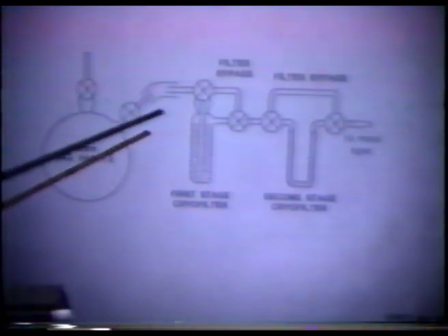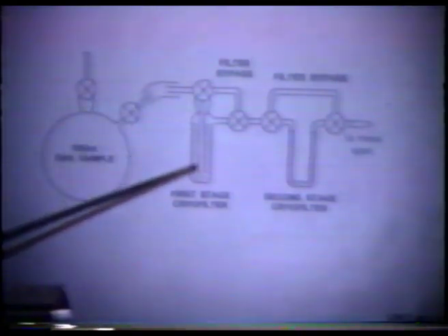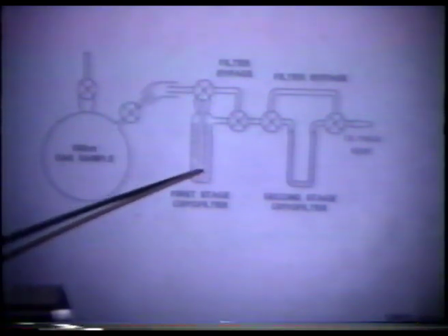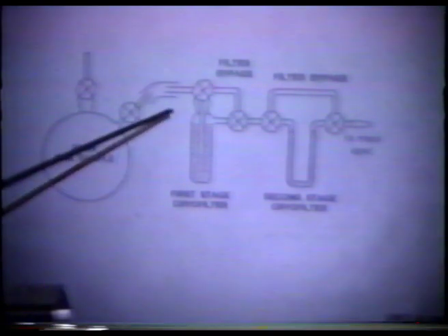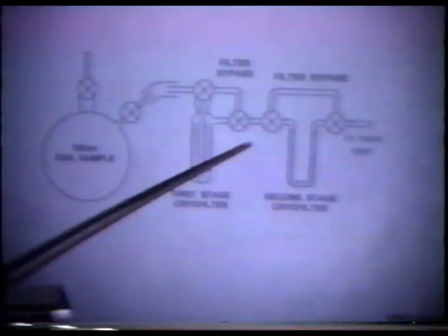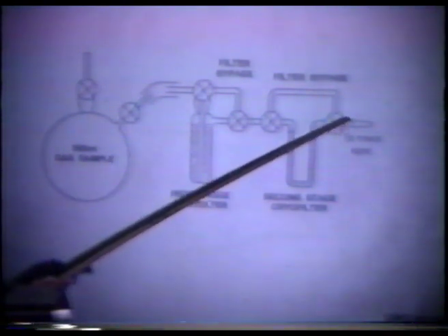In Texas, Ben Bush received these flasks, and to do the mass spec analysis, there's a lot of deuterium in here of mass 4. Now, deuterium of mass 4 is going to be a very big interference trying to measure helium. Therefore, we pass this through a cryo filter. This is activated charcoal at liquid nitrogen temperature. This would remove the deuterium and oxygen gas. One filter was not quite enough, so we even went through a second filter. And so any D2 and O2 gases got hung up in this activated charcoal filter at liquid nitrogen temperature, and mainly only the helium would go on through to the mass spec.